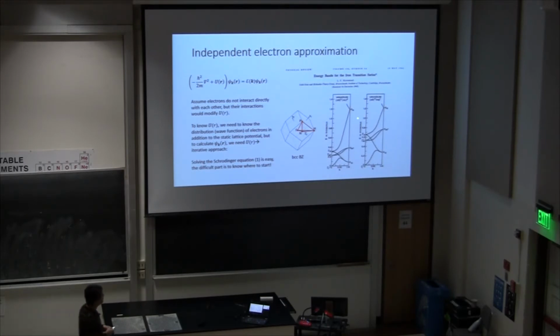Now, this is calculated for vanadium from two different starting points. Vanadium has 5 electrons in its valence shell. You can start from, let's say, 3d3 4s2, or you can start from 3d4 4s1. That means your starting potential will be different between these two cases. Simply, you arrange electrons differently between d shells and s shells. And if you do the calculations, you see that overall they look the same.